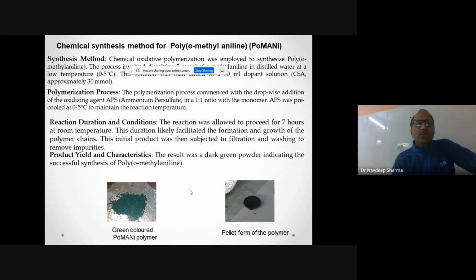Basically, this ammonium persulfate is also pre-cooled at 0 to 5 degrees Celsius to maintain the reaction temperature, because if we do not maintain the temperature, then there is a possibility of a secondary polymerization process, which would not be useful for the desired conducting polymers.